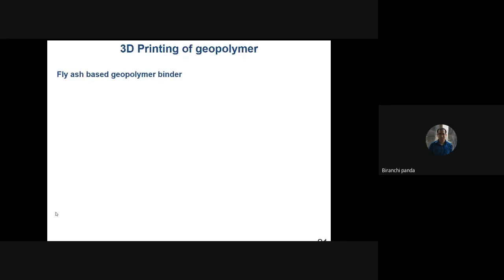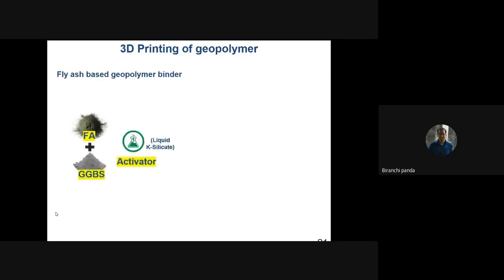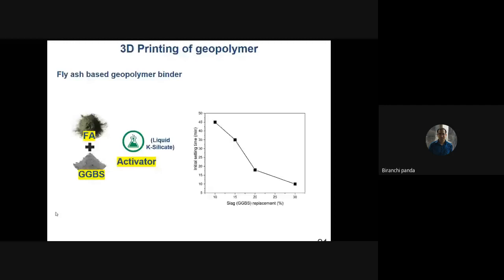So for that particular application, we developed a geopolymer material. Again, it's a more complicated matter, so I'll quickly skip these slides. But before skipping, let me give a very brief introduction to this material development. Here we used some fillers, GGBS, and some basalt material, because we came to know that a similar composition was available on Mars. That information was provided by the competition organizer. Then we used some basalt-kind of material, and we made sure the compositions are similar to the material available on Mars. And then we created this geopolymer mix, where the activator or the chemical component,